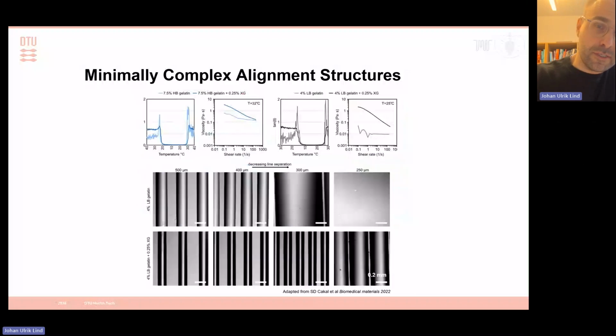So we essentially relied on very common gelatin inks that you can, of course, melt, has a well-defined melting point. Post-extrusion, it gelates, then you can cross-link it. In our case, we used the enzymatic cross-linking. And then we coupled a stiff substrate with a softer, lower concentration gelatin, where we then print filaments of the soft materials on top of the stiff material.